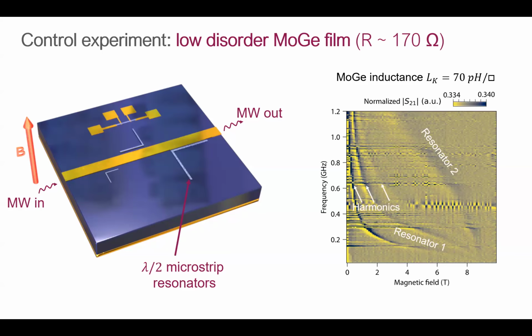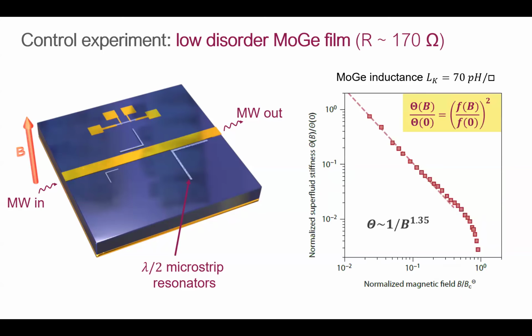And you see that they all converge towards a critical magnetic field, which is actually the Hc2 of the material. Now I can take one frequency as a function of B and square it, and I get the superfluid density, assuming I know the superfluid density at zero magnetic field. I normalize it, and this gives me the evolution of the superfluid density as a function of magnetic field. I normalize it with this Hc, and what you see is a power law decay suppression of the superfluid density in this vortex state.